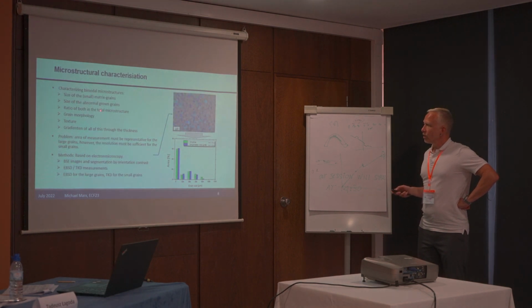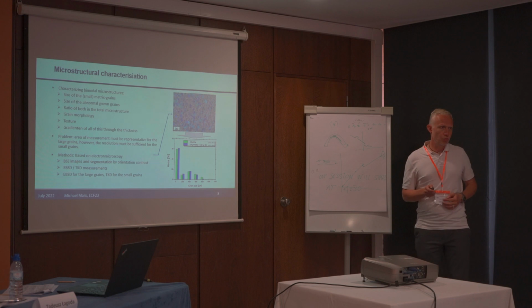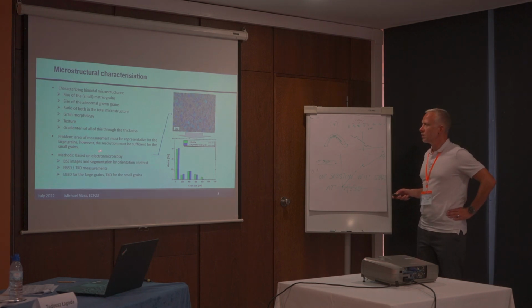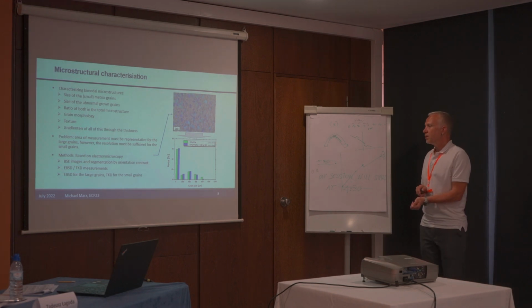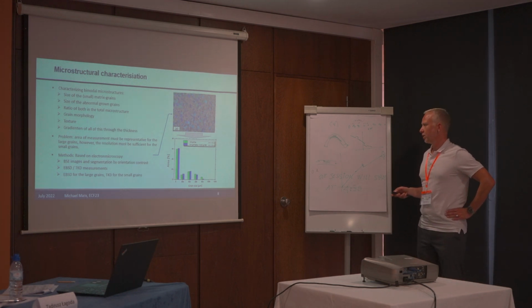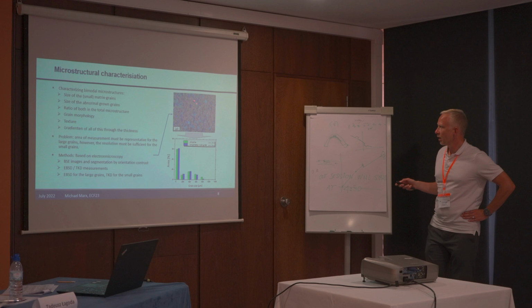To characterize our microstructure, we measure the size of the small matrix grains, the size of the abnormal grown grains, ratio of both, grain morphology, texture, gradient through the thickness of the plate, and we do this by electron microscopy based techniques, backscatter electron images, EBSD or transmission EBSD. We also use it for the small grains which are in the nano-sized area, and then we get here maybe this size distribution of such a bimodal microstructure with some small grains, and here about 400 nanometers. It's not micrometers, nanometers here. The grain size here of the ultrafine grains.